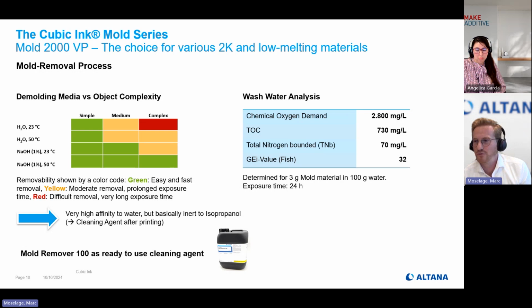It is a value for the mortality of fish eggs. Basically, it's a pretty German value, and this is what we determined here. The basis for this material is that we had 3 grams of mold, put them into 100 grams of water, and let them expose for 24 hours, which is pretty a lot.